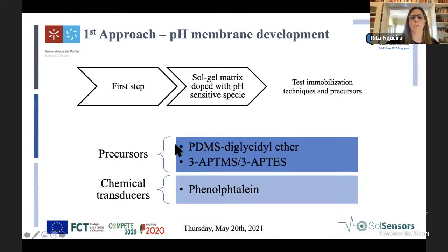We used as precursors polydimethylsiloxane diglycidyl ether (PDMS) and 3-aminopropyl trimethoxysilane (APTMS) or 3-aminopropyl triethoxysilane (APTES). It depended on what we used. We used always PDMS, and then we changed APTMS or APTES. And then we used as chemical transducer the phenolphthalein, a widely known indicator.